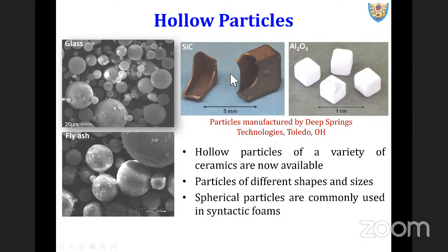In addition to the spherical one, we have cuboid ones, silicon carbide, Al2O3. But as these have corners, these induce stress concentrations within the system once you disperse in the matrix. And thereby, generally, we don't prefer these. We prefer the spherical. No stress concentration, and there will be uniform spread of a resin around this, because that is a crucial parameter in composites, wherein we talk about the wetting of matrix onto the reinforcement or a filler.